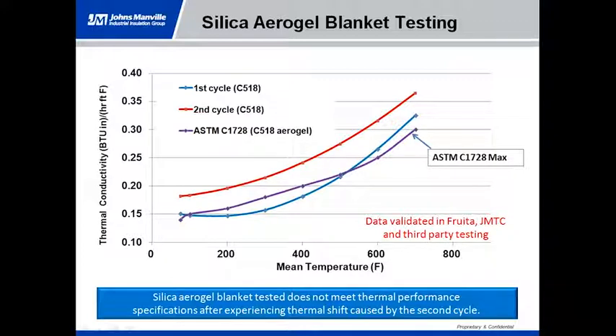Now, we did the same test with the silica aerogel blanket, and what we found is this. We start off with the ASTM C1728 maximum, which we saw in an earlier slide, and just below that, the blue line, we see the first cycle of flat testing that we had done with the silica aerogel blanket. For the most part, you can see that most of that product performs below the line, which is good. Some of the higher temperatures it's above, you know, does it pass, does it fail?